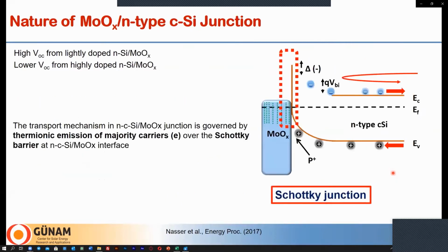So this observed degraded cell performance with increasing crystalline silicon doping concentration suggests that the transport mechanism at the N-silicon and molybdenum oxide junction is governed by Schottky barrier thermionic emission of majority carriers, and not by diffusion of minority carriers. Now, with increasing N-silicon doping concentration, the Schottky barrier width itself for conduction band edges between molybdenum oxide and N-silicon reduces, and now electrons can tunnel and reach the aluminum contact, and the whole selective capacity of molybdenum oxide reduces.